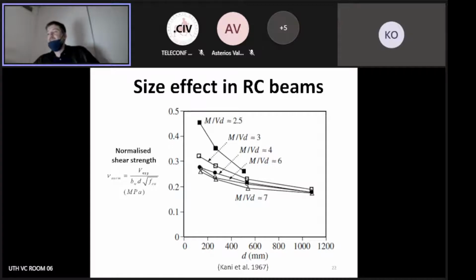What does it mean? It means that somebody observed a long time ago that if we design and test a few identical beams where the only variable parameter is effective depth, we actually will observe lower shear strength at failure in the larger elements. And this is more pronounced for elements with a over d around 2.5, so shear critical. Once the element becomes more slender and resists loads more through bending than shear, then this effect is less significant. This is a problem, because if we are using the same equation without this reduction factor, we will end up predicting the same shear stress level across the span of the depth, and this will end up having large reinforced concrete members grossly under designed, and this is something that can cause a failure of the structure.